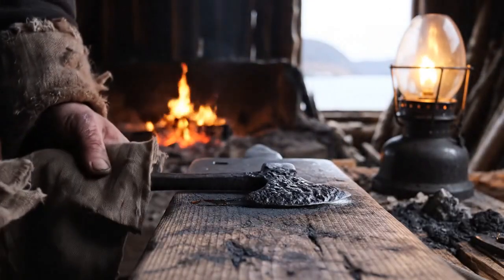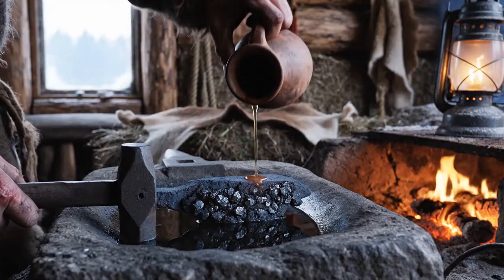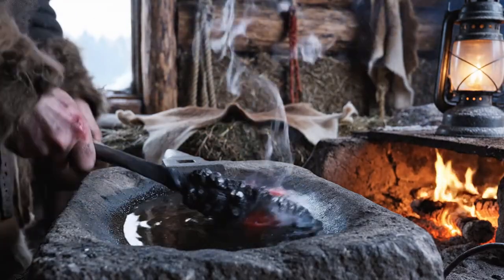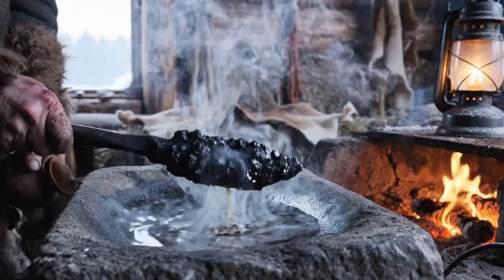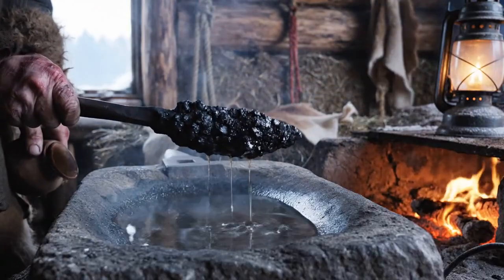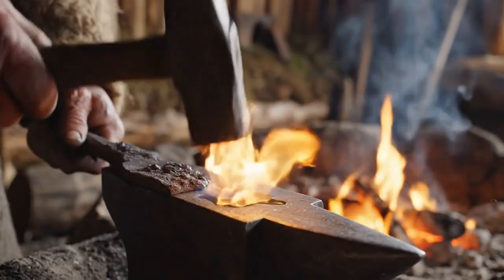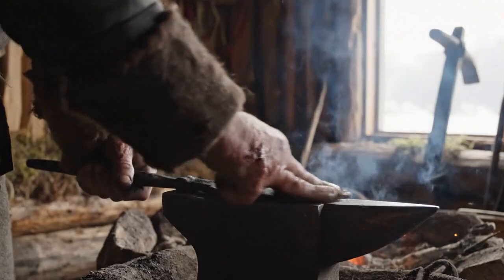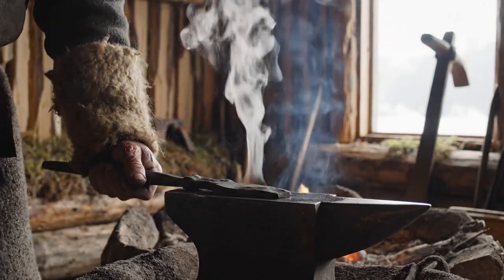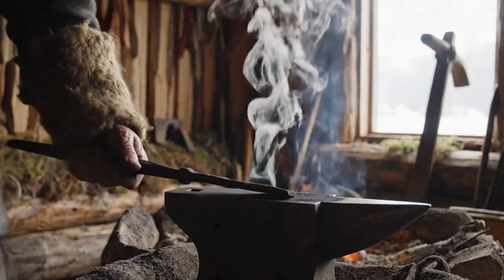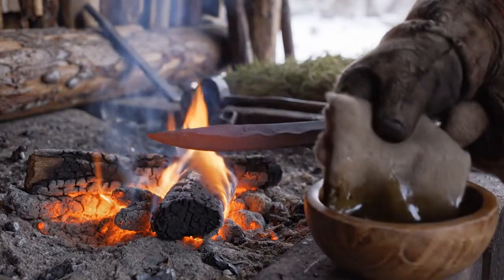No thermometer required. Hold the blade over the heat and watch the flat surface. It will shift from its usual gray to a pale gold, then to a deeper straw yellow, then to a blue purple. The moment you see that first blue tinge appear, pull the blade from the heat. That blue color is the signal. It tells you the iron oxide layer has formed, is active, and is ready to receive the oil.